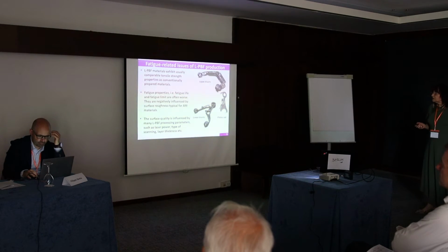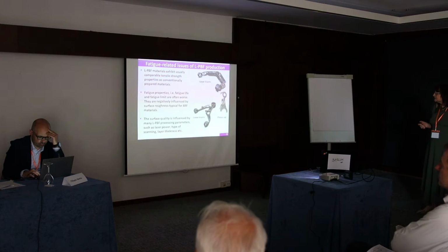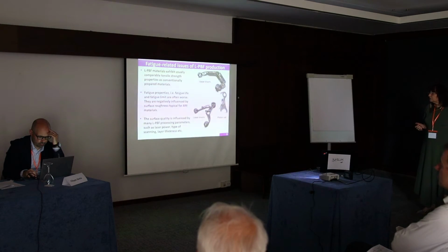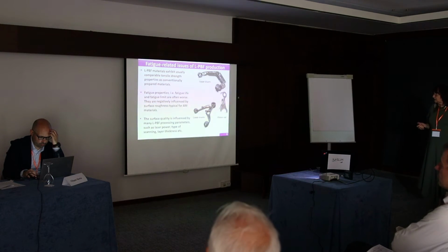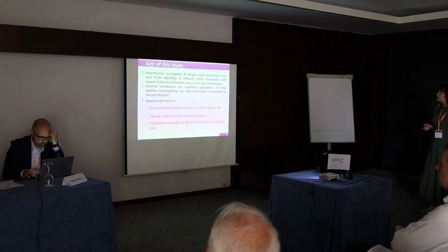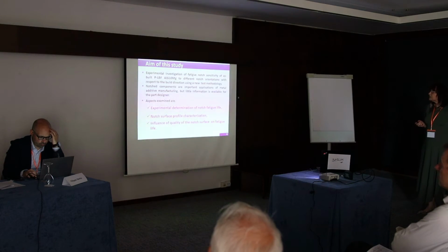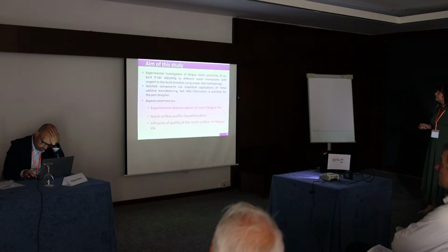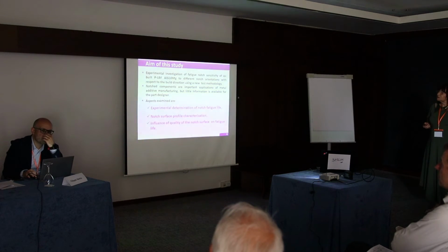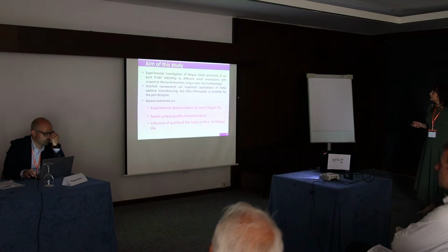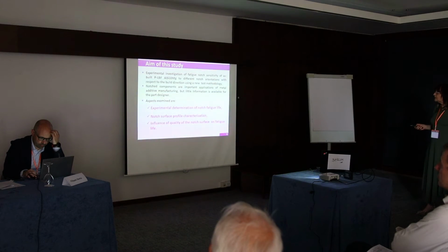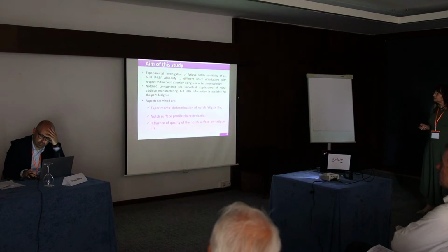The surface quality is influenced by many laser powder bed fusion processing parameters, such as laser power, type of scanning, layer thickness, etc. The aim of this study was experimental investigation of the fatigue notch sensitivity of as-built laser powder bed fusion aluminum alloy for different notch orientations with respect to the build direction, using a new test methodology.